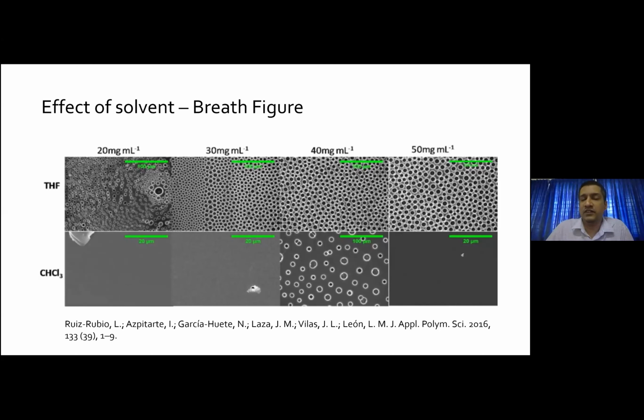They believe that THF allows the water to readily settle onto the surface, and then slowly the water droplets evolve. Once the water deposits onto the surface, the THF prefers to stay with the polymer, or the polymer doesn't like to leave the THF because it would have to become a highly concentrated solution. There is always a natural tendency for any dilute solution to remain dilute. So the solvent is phase separated, even in the case of THF in the presence of water.